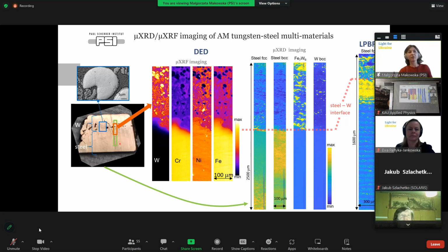So this is a cross-section of a sample produced with this directed energy deposition technique. So here we have steel, and on top of it, we have several layers of tungsten. This is a very interesting combination of two materials that actually would have application in reactors, but in fusion reactors. So we're using fluorescence and diffraction microimaging. We can see nicely the distribution of these elements at the interface. We can see the mixing, but also we can see formation of intermetallics from the diffraction contrast.